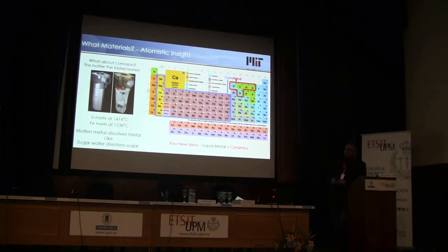Generally speaking, there's lots of compounds that can be formed that are very stable between, let's say, 1,000 degrees and about 1,500 degrees C. There's a lot of oxides and a lot of different compounds that can form in that regime. But if you go well beyond 1,500 degrees C, you get to this new regime where a lot of the materials that may be stable around 1,500 degrees C, a bunch of ceramics, actually start to lose their stability. And once you get to about 2,000 C and above, there's a smaller group of ceramics that are very, very refractory that remain stable.